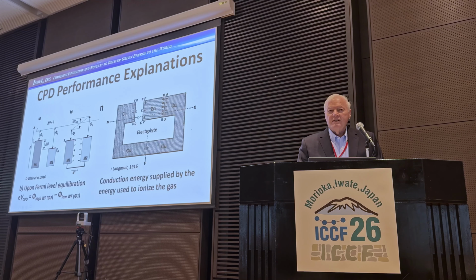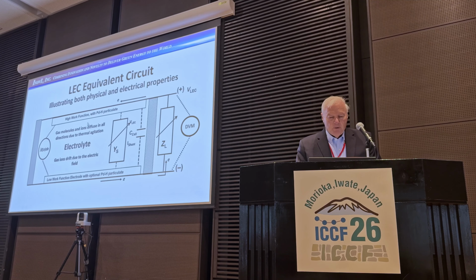Here's an equivalent circuit, or this looks kind of like one of the flat electrodes. We have the high work function electrode, the low work function electrode. We connect the two of them through an external load. And in this case, we have a resistance box that we can adjust, put a DVM out there. It doesn't take a lot of expensive electronics to do this. And when you connect them, the Fermi levels equilibrate. From this point on, it's all involved in the electrolyte. And allow me to define electrolyte as any medium that will transfer electrons or charge, ions, anything with mobile ions, or will transfer charge. And the thing we've used most is gas.